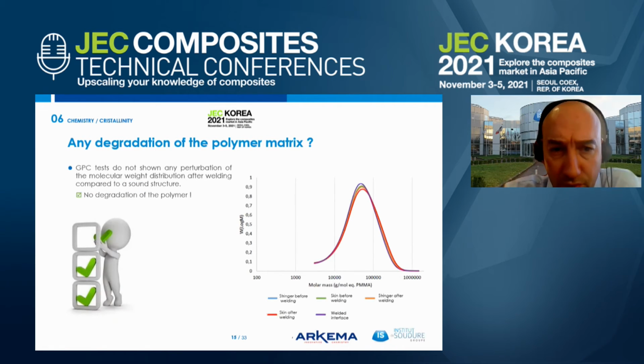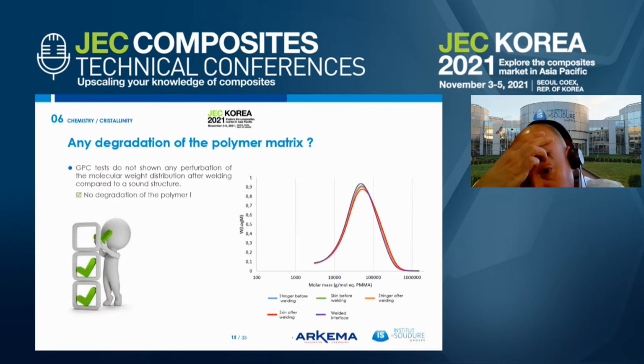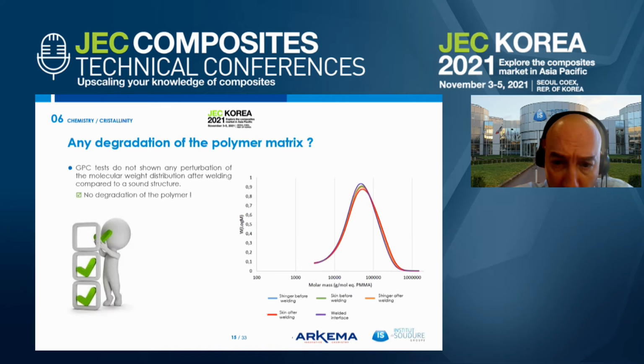About chemistry, because this is also important to demonstrate, at least to highlight the fact that we are not degrading the polymer at the interface, very close to the susceptor that is generating all the heat in order to induce the melting of the thermoplastic. So if we have a look at this GPC, molecular mass repartition, this is an illustration on PMMA, because we can also weld PMMA, meaning the Elium resin from Arkema. But for any kind of polymer, we have done this, and we are not degrading the polymer at the interface. Of course, we are working on the crystallinity level after welding. This is in progress and needs to be optimized, but we are not degrading the polymer.